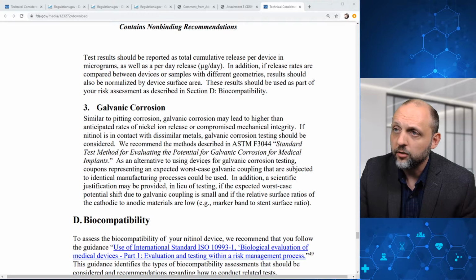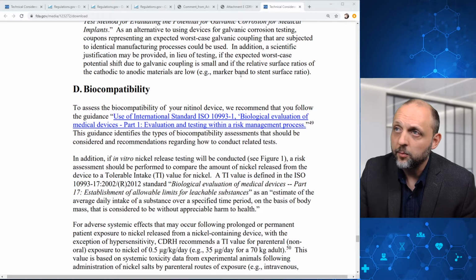And as an alternative to using devices for galvanic corrosion testing, coupons representing an expected worst-case galvanic coupling that are subjected to identical manufacturing processes could be used. In addition, a scientific justification may be provided in lieu of testing if the expected worst-case potential shift due to galvanic coupling is small and if the relative surface ratios of the cathodic to anodic materials are low. And here they give an example of a marker band to stent surface ratio.